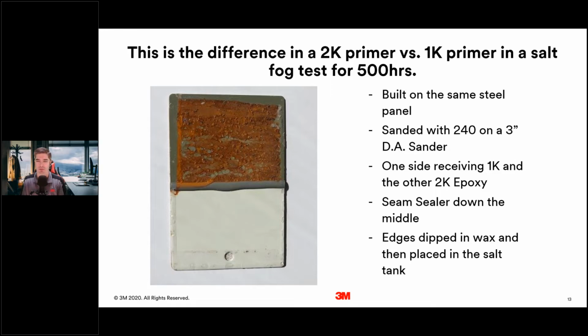And once it starts, it'll work its way under paint, it'll work its way under seam sealers, and cause some problems for our repairs. And especially if they don't get out to do a reinspection for, say, 3 to 6 months sometimes because they're overloaded, corrosion may start in these areas and we don't see it, the customer doesn't see it, but all it takes is somebody that knows what they're looking for to crawl under a vehicle with a flashlight and say, hey, it looks like it's already rusting, we've got some problems.